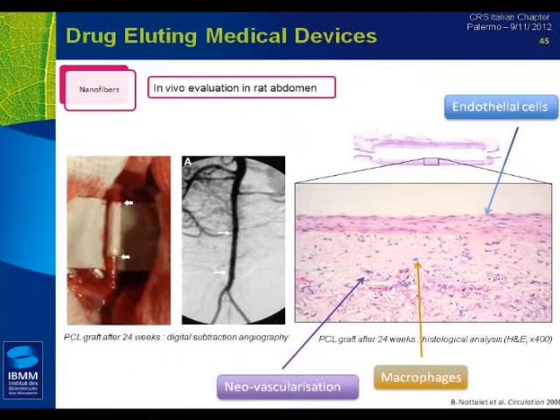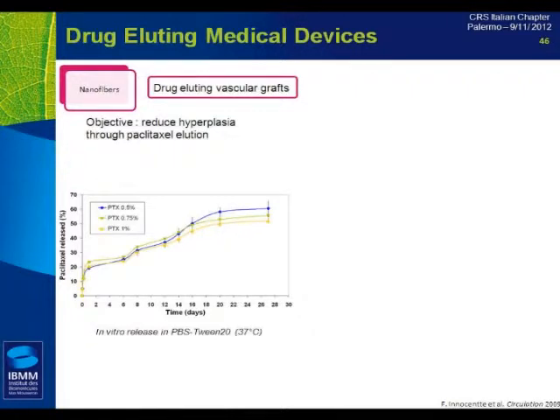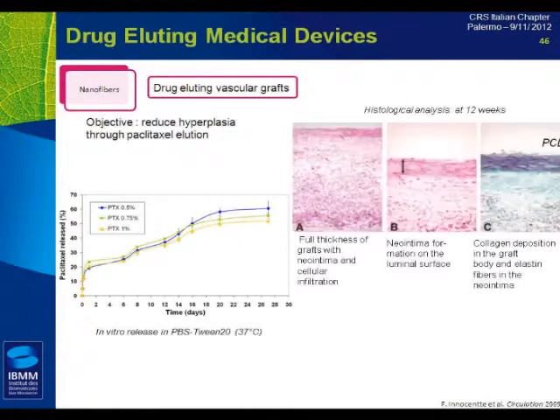The problem is that you don't have a monolayer of endothelial cells. You have only a multi-layer, and that's what you want to avoid because it's more or less already hyperplasia in that case. So what was done, especially by Delia Mandrakia, was to entrap some paclitaxel, an anti-proliferative drug, into those nanofibers. We looked at the release of drug depending on the concentration over time. And then we looked at the effect of those eluting nanofibers into the meshes, into the grafts.